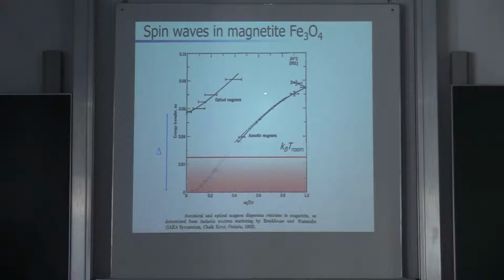Now, the spin wave dispersion up to these energies is roughly parabolic. So for all properties of magnetite at room temperature, you can completely forget about the optical magnons. It behaves like a very nice ferromagnet. Now, YIG is a little bit more complicated, and you cannot do this simply analytically anymore.